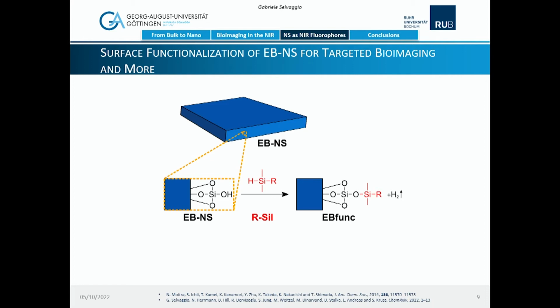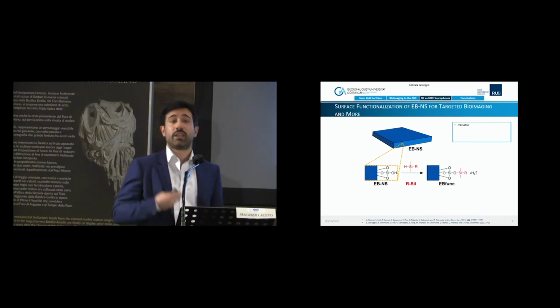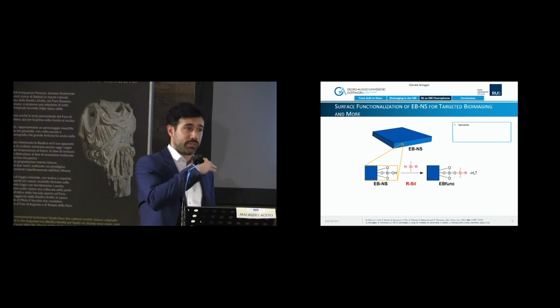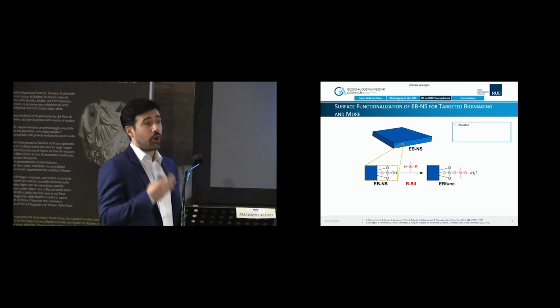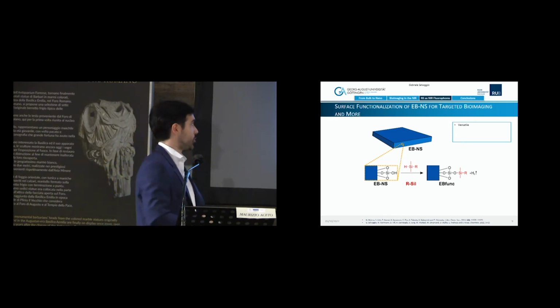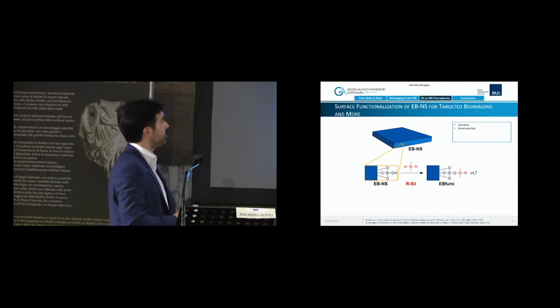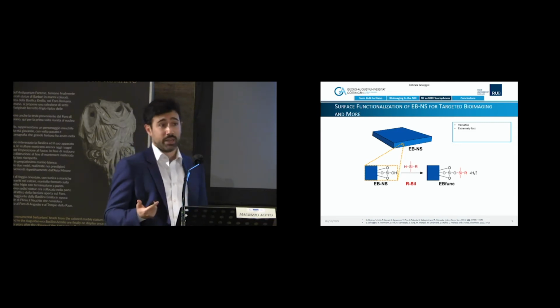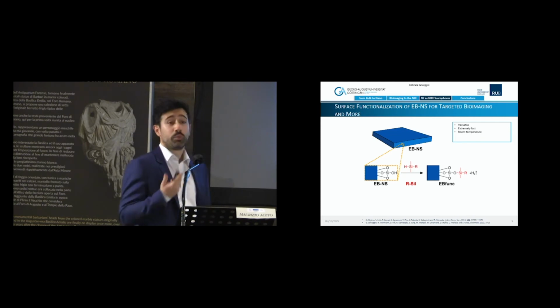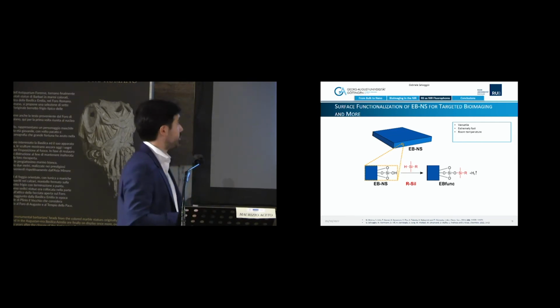And this is a protocol which relies on silicon hydrogen activation by hydrosilanes. And this is a very versatile protocol because you can covalently graft onto the surface of the nanosheets multiple R groups of diverse chemical nature. There is a huge library about them. And also the reaction happens in 5 minutes, so it's really, really fast and at room temperature, therefore, of course, appealing for this reason too.